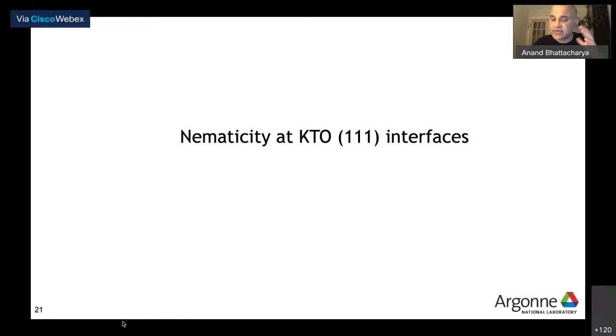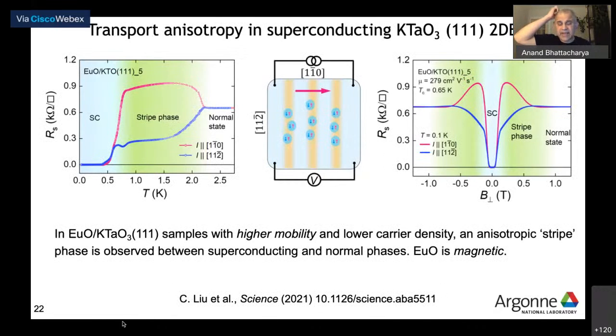But what was really mind blowing to us was what I'm going to show you next, which is that in samples with slightly higher mobility and lower density, what we find is that when we cool down the sample from the normal state, before we become superconducting, the resistance is measured in a simple van der Pauw type geometry, where we are measuring along the edges of the sample, say, in the square that you see in the middle. You do voltage and current on the sides going one way and then the other way. And we've done it every other way you can think of. What you find is that the resistance,